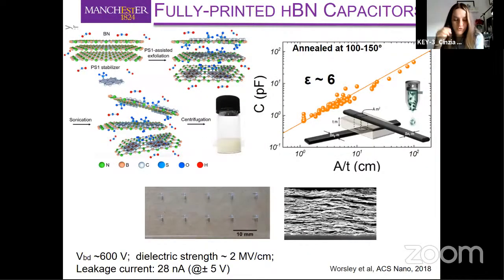So moving next, as I mentioned to you, our final goal is to produce a fully printed integrated circuit, and to do so, we also need obviously transistors and diodes, but we also need the passive components such as capacitors. And capacitors are very easy to make because our exfoliation approach also works with hexagonal boron nitride. And so we can get highly concentrated dispersions of hexagonal boron nitride in water that can be implemented into the heterostructure. So the capacitor has exactly the same structure that I showed you before for the photodetector, the graphene at the top and at the bottom, and then we replace the tungsten disulfide ink with the boron nitride.